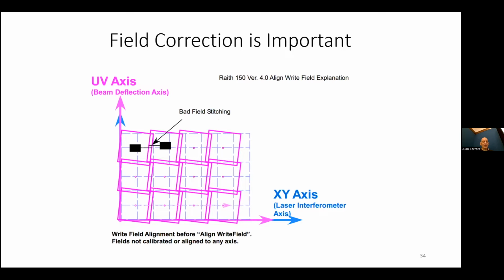So here's what happens if you don't have a field-corrected beam. You get a lot of fields that might be 500 microns across, or maybe they're 520 microns across, or some other number. They're not always rotated so that the axes of the beam deflection align with the XY axis of the stage of the mechanical deflection. And in addition, there could be pin cushion or a trapezoid keystone, other kinds of effects.